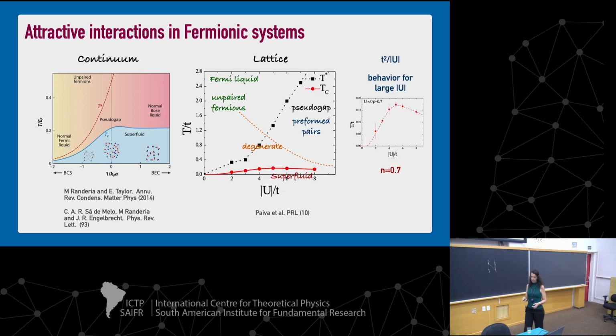And this is something interesting. And so here is the same plot as before, but with numbers. It's not a sketch anymore. So the superfluid region is very tiny down here. And this line here, T_P, is the pairing formation. This dotted orange region here is where we have the degenerate Fermi gas. Here we have the Fermi liquid with unpaired fermions, and here we have preformed pairs that, when reaching down here, condense. And this is a blow up of this region here, obtaining the critical temperature for a given density as a function of U over T.